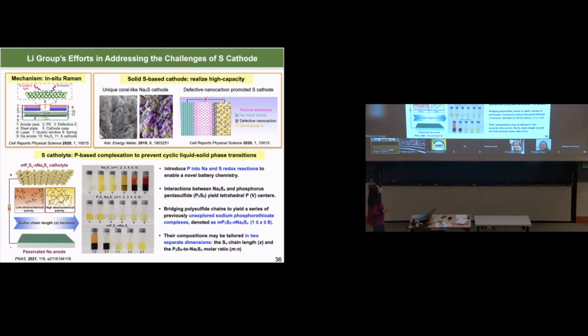And we are also able to control the molecular structure of the material by tailoring it in two different dimensions. One is we can control the chain length right here, and we can also control the molar ratio between the phosphorus-based compound and the sodium-based compound here.